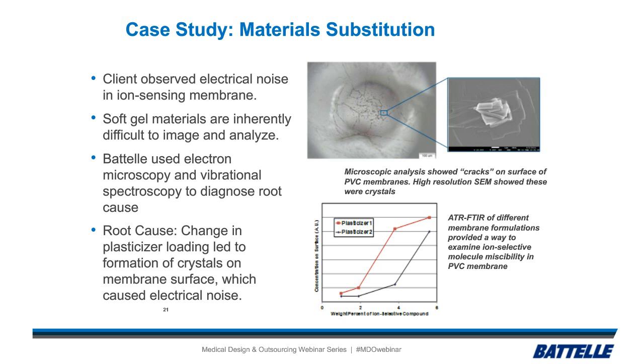So the question was, why was this happening? This was clearly the reason that the ions couldn't get through. We were in a crystalline phase instead of miscible with the hydrogel. So we looked into it a little bit more and asked questions about what had changed in the recent past. One thing was that the concentration of the ionophore had been increased to try to get a better signal.